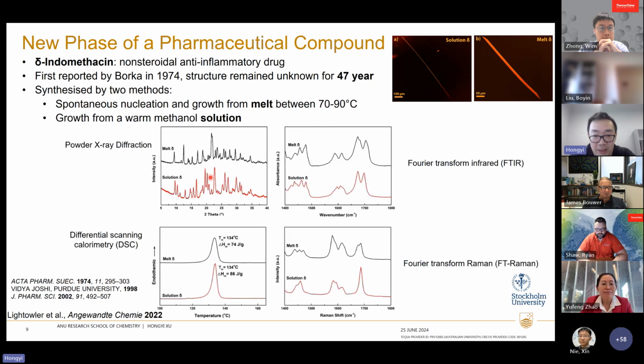And then when people looked at all the characterizations of these two, they believed they were the same polymorph, just grown in two different ways. If you look at all these characterizations, they are very, very similar. But are they really the same phase? Now we know they are different phases. If you look at the powder, there are subtle differences between the powder patterns.